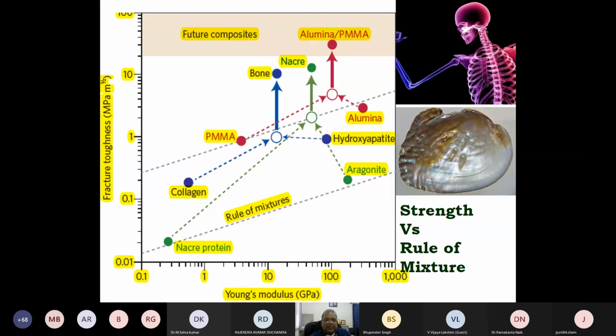Right? Same thing, the nacre, the seashell. Seashell is a composite of a protein called nacre protein and aragonite. Aragonite is one of the phases of calcium carbonate. Calcium carbonate has three phases: calcite, vaterite, and aragonite. If you look at the fracture toughness of nacre protein, it's very low. Aragonite is here, it is also very low. And you see the nacre is somewhere here. Right. So all rules of mixture are defied in the naturally produced nanocomposites in terms of strength.